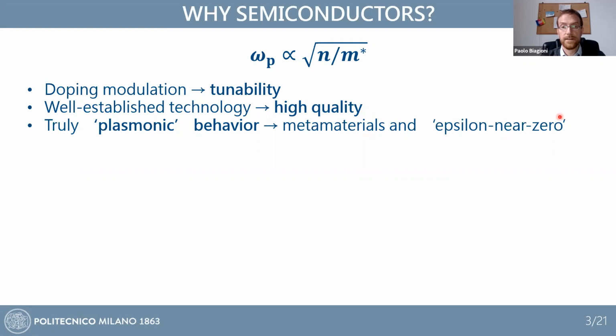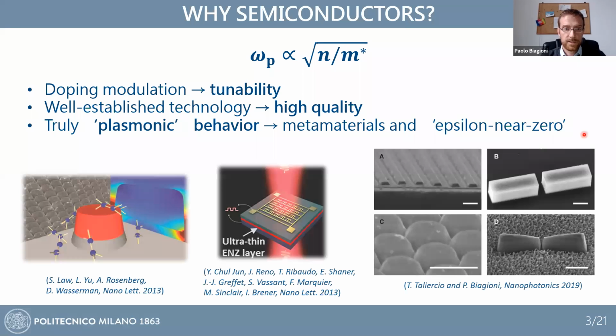And also, as we will see, these materials allow for direct access to the epsilon-near-zero phenomena, which require a vanishing dielectric constant, which is of course not the case for perfect conductors in the mid-infrared. And so we started seeing in the literature examples of semiconducting antennas made both from group 4 and from 3-5 alloys, and fabricated with different techniques, as much as we have for metals, basically.